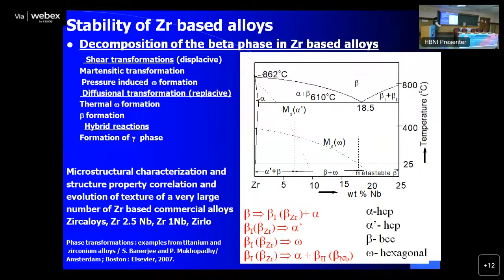and if you are having more niobium, then you will have the omega phase. Now, the alloys of interest are zirconium 1 niobium somewhere here, and zirconium 2.5 niobium somewhere here. But all of them have beta phase, which can have compositions in that range, and they all can form the omega phase also, which is not a desirable phase, it is a brittle phase.